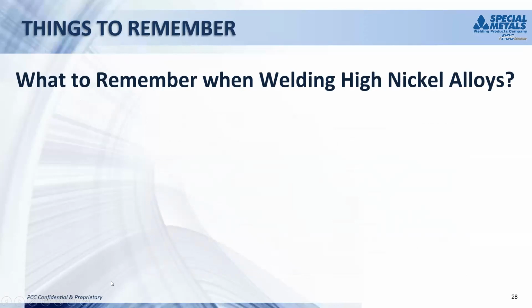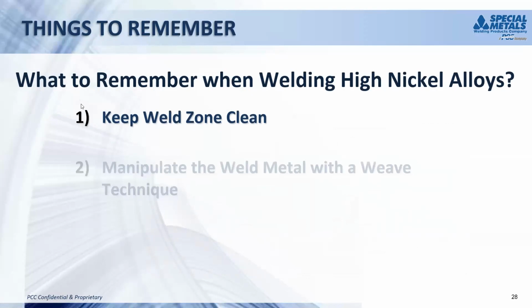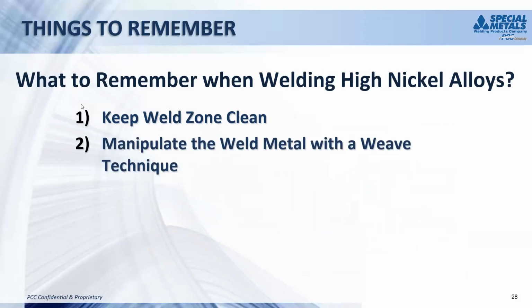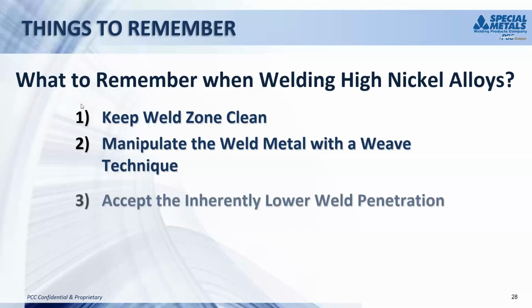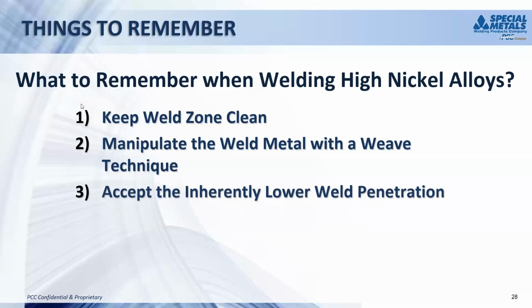So what do we need to remember when we're welding nickel alloys? We've got to keep the weld zone clean. When we made the alloys, we made them with low sulfur. Please don't introduce any more sulfur. Next, we have to manipulate the weld metal with a weave technique, and that weave technique has to include a brief hesitation at each side to let the puddle catch up with the arc. And we have to accept the inherently lower weld penetration that you get with nickel alloy base metals, and we have to open up the joint, and we have to make thinner lands.